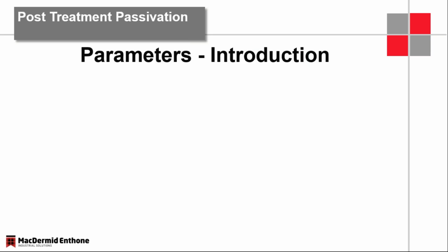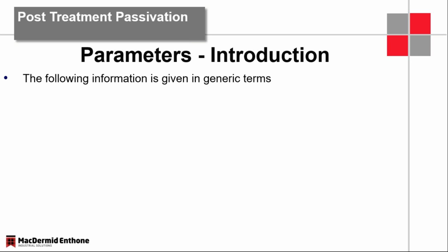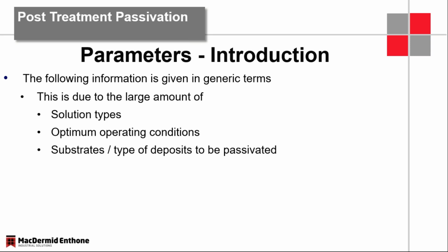So when I start talking about parameters, I want to just mention that one of the good things about chromates and Passivates is that they are adaptable. The information that I'm going to be providing to you is dependent on what you're doing in-house, predominantly on the plating line, what solutions you're using. Acid versus alkaline could have completely different operating conditions for the same product. That's because the grain structure is different.